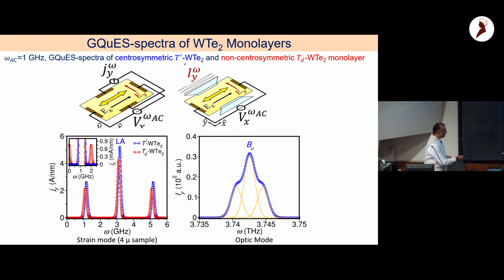You have a peak at the LA phonon frequency. This is like IR spectroscopy now, because Berry curvature dipole is basically absorbing that phonon. You get a peak at the phonon frequency of 3.2 gigahertz. But you also have Stokes and anti-Stokes peaks now, which are associated with the applied frequency. They are basically omega, 2 times omega AC plus minus omega naught.